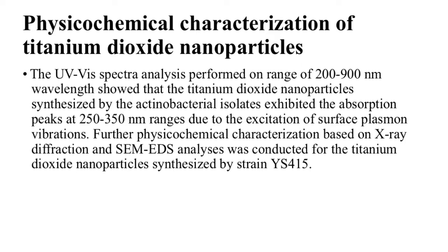Physicochemical characterization of titanium dioxide nanoparticles. The UV spectra analysis performed in the range of 200 to 900 nanometers wavelength showed that the titanium dioxide nanoparticles synthesized by the actinobacterial isolates exhibited absorption peaks in the 250 and 350 nanometer ranges due to the excitation of surface plasmon vibration.